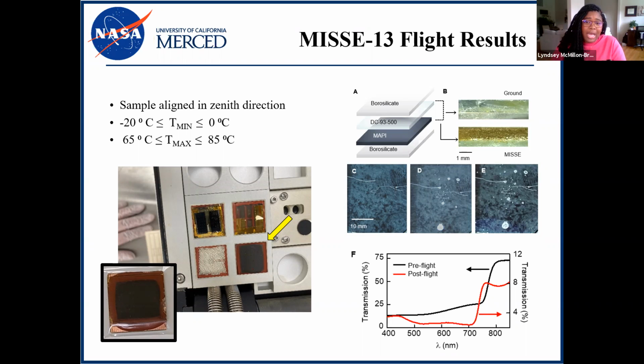So the sample was aligned in the zenith direction on the International Space Station, which means it was generally pointed towards the sun. And the MISSE flight facility holds these samples in an aluminum frame that has a fairly large heat capacity. So that kept the sample slightly warmer during the eclipse period of the orbit than would happen if they were away from a spacecraft body and allowed to radiate into the deep space. So for that reason, our samples saw a minimum of about -20 degrees C and a maximum temperature of 85